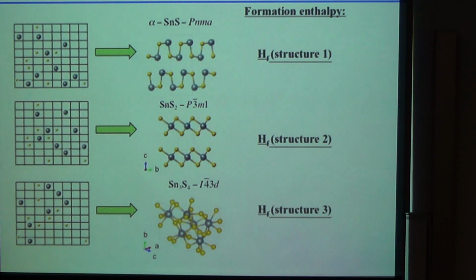The important thing before I go to the results of these methods is to explain how we work with the energetics. If you have some particular initial random structure, we relax it to get a particular compound with a specific space group. This just comes out of the calculation. We calculate the formation enthalpy. Basically it's the difference between the enthalpy of the compound minus the enthalpies of the elemental compounds at a given pressure and temperature. So we work with these formation enthalpies.